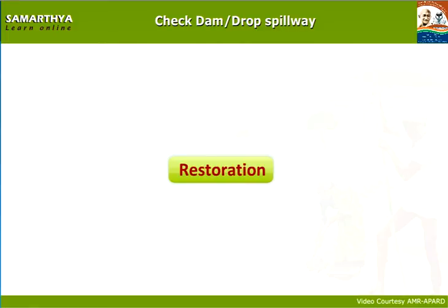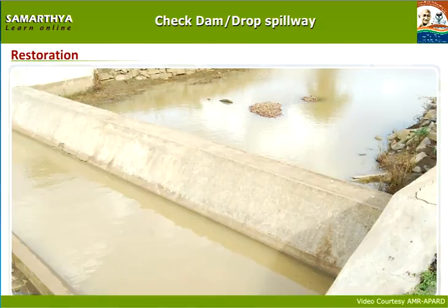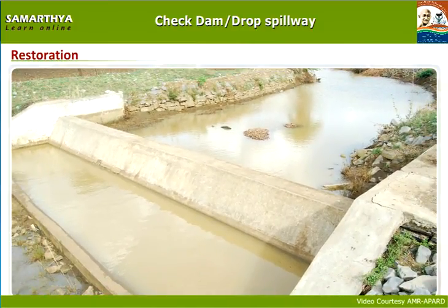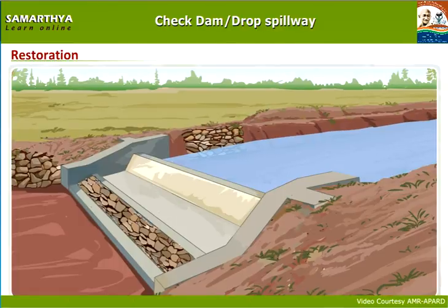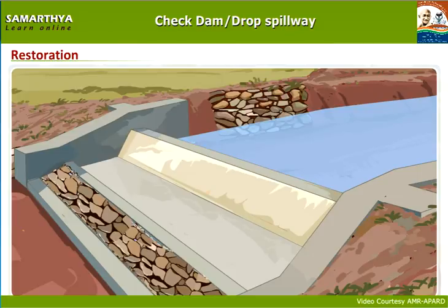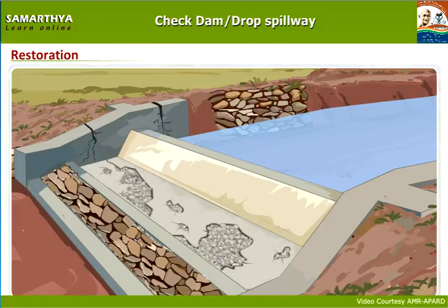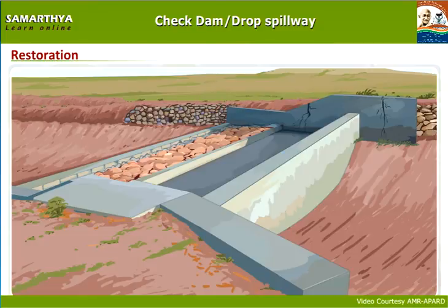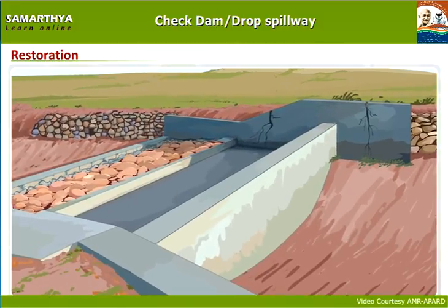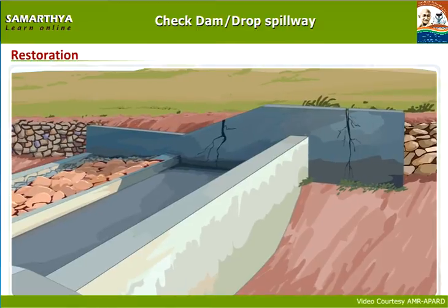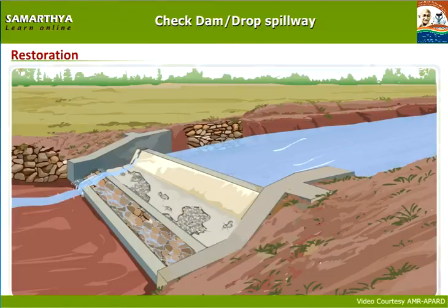Restoration of check dam. Continuous supervision is required even after constructing the check dam. Because check dam is a cement construction, in due course of time, it is a common phenomenon that cracks may develop in the walls of check dam due to flow velocity, cracks in apron, cracks in body wall on both sides of main walls, that is, upstream side wall and downstream side wall. Moreover, there may be leakages even at the joints between body wall and guide walls.